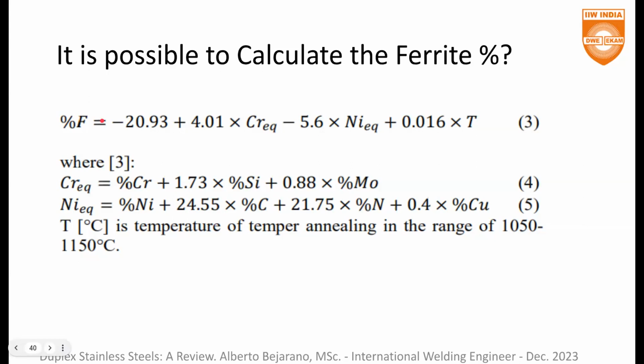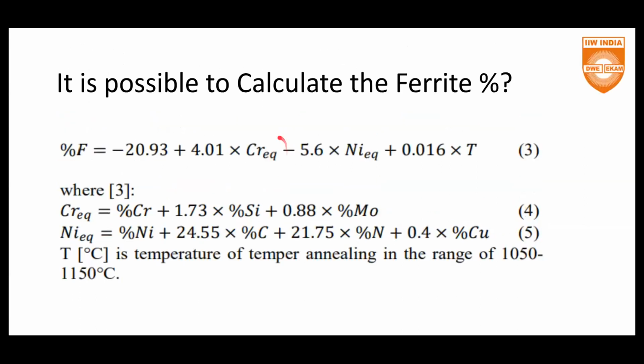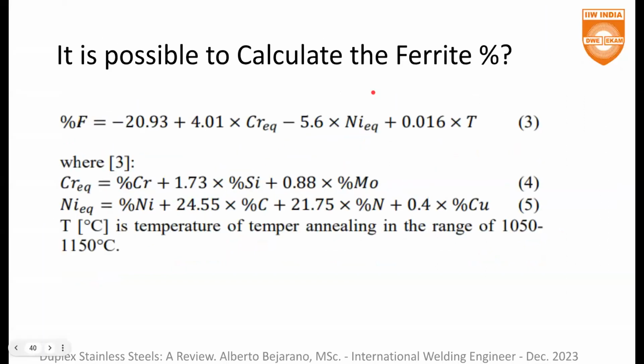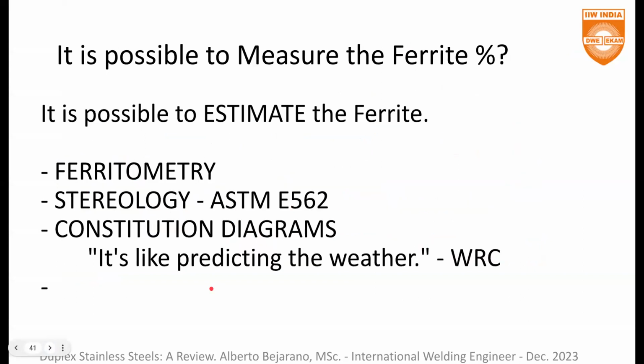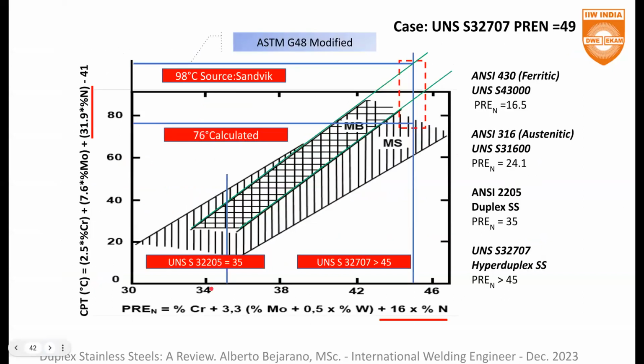We calculate the chromium equivalent and nickel equivalent, and the temperature of temper annealing. Listo? This is very important. The temper annealing, which is between 1050 and 1150. Okay, but this is not for welding, so take care with that. Oh, pretty good.